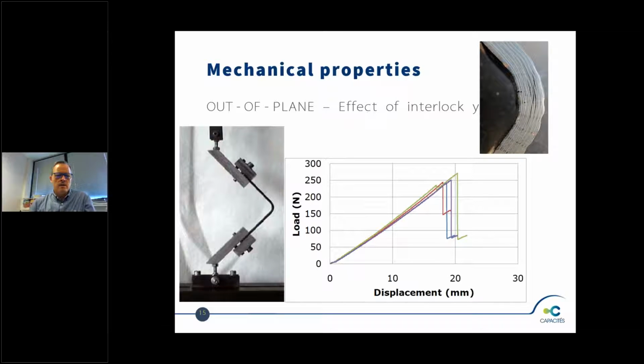Then at that time we developed a test, and we are quite familiar now with developing tests for customers, because many customers now come with a new idea, a new test to achieve, and we can both cut the specimens, design the test, and practice the test. So this is basically the load displacement curve that we have by unfolding the specimen, which have a L shape.